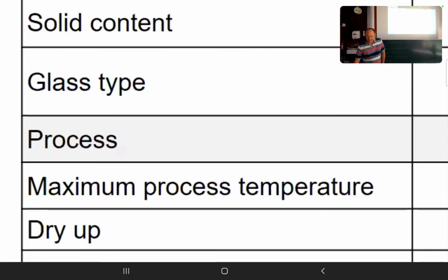And of course, glass melts at a higher temperature. Typically, for instance, when you have vanadium oxide or a mixture of vanadium oxide and other oxides, you can create something like a eutectic, or you can have quite low melting points. So for vanadium oxide-based glasses, you have a process temperature of 340 to 400 degrees centigrade. And the silver content, again, is roughly 80%. You can again use a needle dispenser, or a stencil print, in order to deposit that material as a paste. And then the chip is placed.